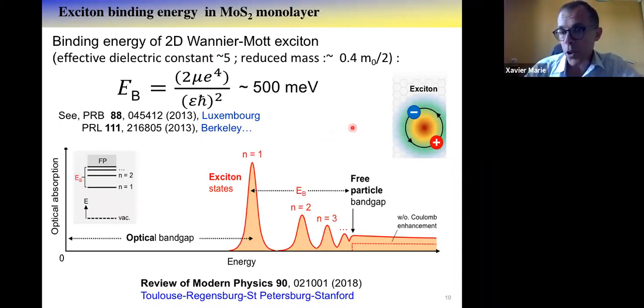And of course, to get information on this binding energy, it's usually very useful not only to detect the ground state of the exciton, the n equal 1, in photoluminescence or in absorption, but also to get information on the excited states. And basically here, you have the optical absorption as a function of the energy, very schematic. A lot of work has been done in many groups to measure the energy position and the characteristics of these exciton excited states up to the free carrier gap. And from this, you can get the binding energy.